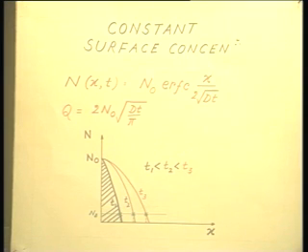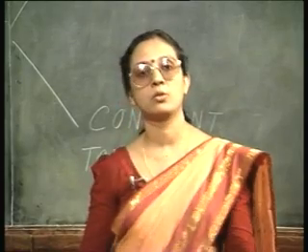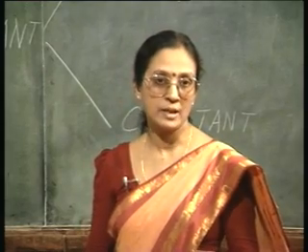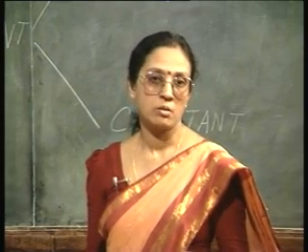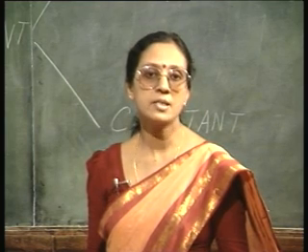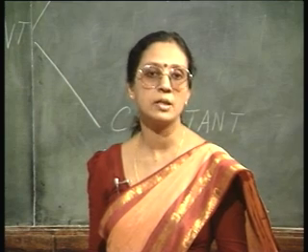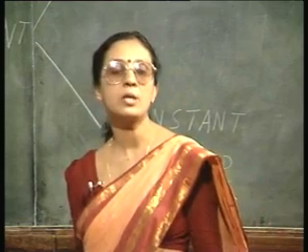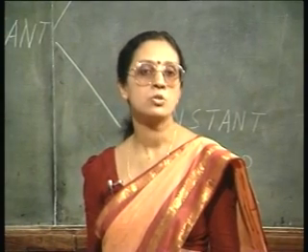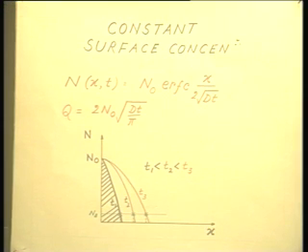This is the constant surface concentration or infinite source diffusion case. In the language of VLSI technology, this is referred to as the pre-deposition. The silicon samples are placed inside a furnace in an ambient containing the dopant — phosphorus or boron — and with the source on, diffusion is carried out at a given temperature for a specified time, so that the doping profile obtained is the complementary error function profile.